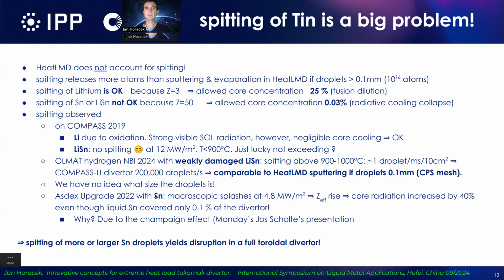On Asdex Upgrade, the spitting of tin, we saw macroscopic splashes really at already this value of 5 megawatt per square meter, and it already increased the core radiation by 40%. So we were really decreasing the power in the plasma by a lot, even though the target covered only 0.1% of the divertor. So it was really a tiny object. So if you extrapolate to the full toroidal divertor, you should multiply by a factor of 1,000, and this would be out of the question.